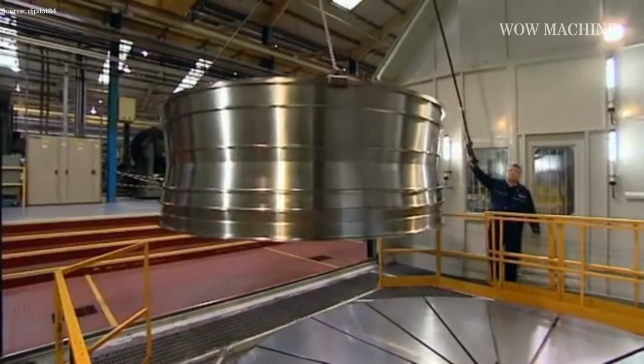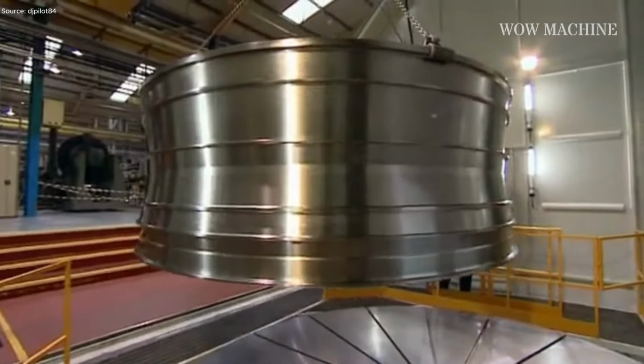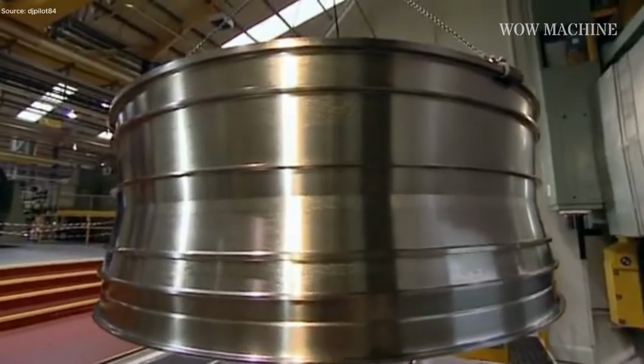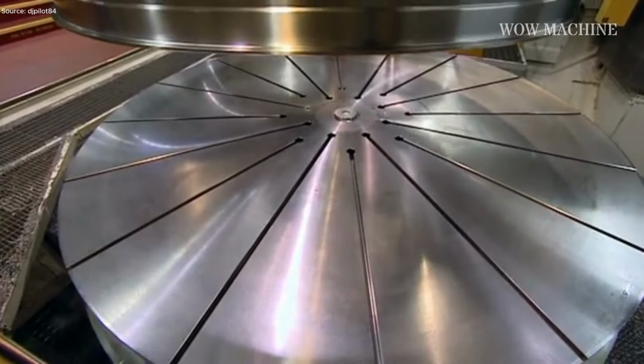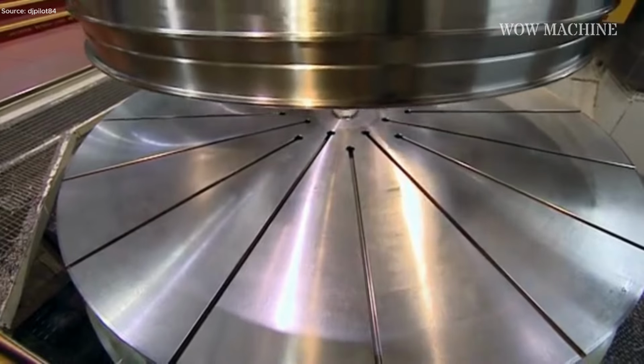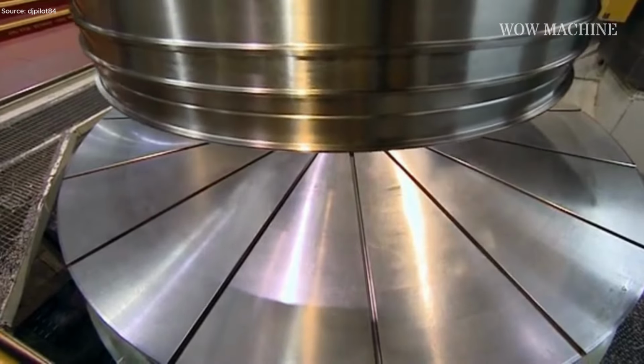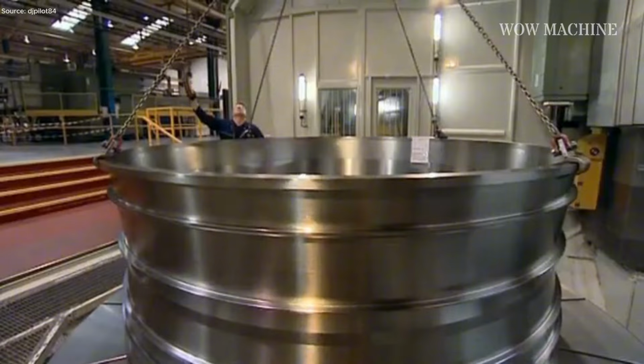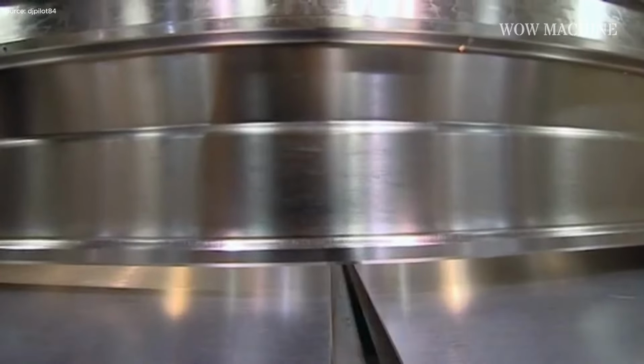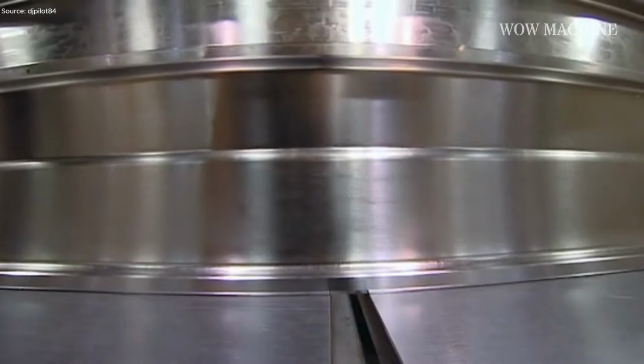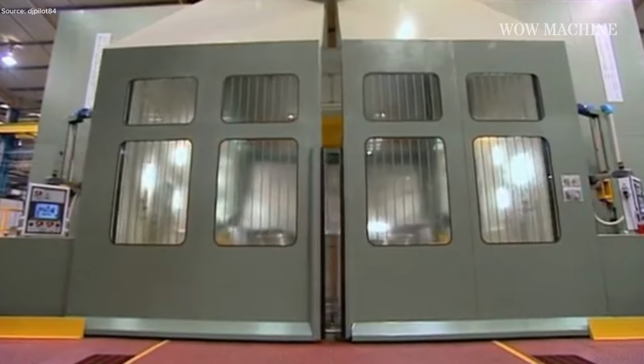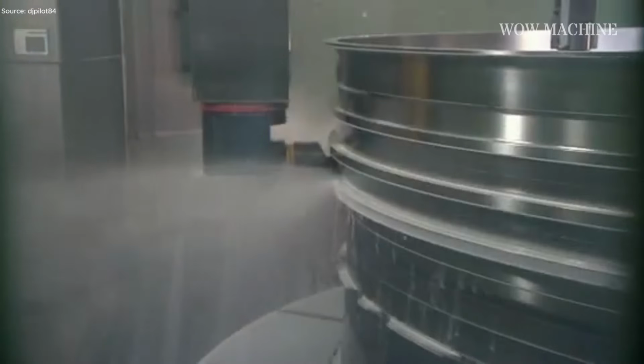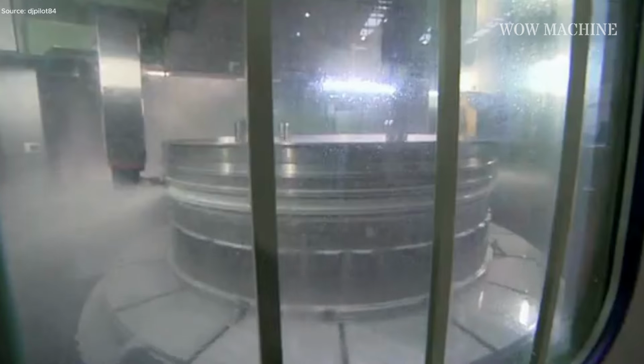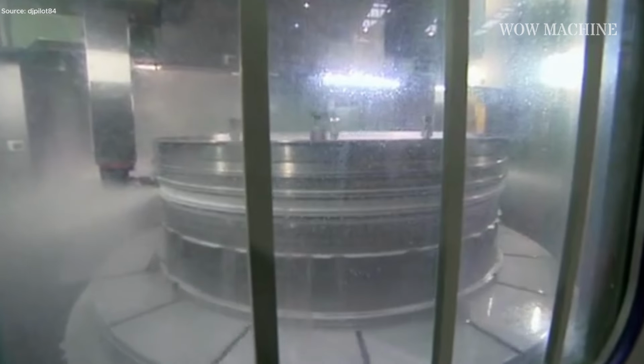Next comes the making of the fan case, the strong shell that keeps the engine's power safely contained. The first task here is machining down a 5-ton titanium forging to less than 500 kilograms, removing almost 90% of its material. CNC machines run up to 90 hours, cutting walls just 2.5 millimeters thick. All titanium scrap is recovered and recycled. One wrong coordinate could turn a week's work into scrap metal, so everyone stays laser-focused.